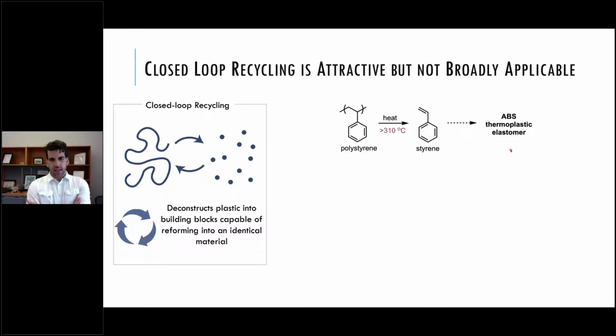A less publicized, but also I think pretty promising commercial route to do closed loop recycling is actually of polystyrene, otherwise known as styrofoam. If you heat this up above 310 degrees Celsius, sometimes you can use catalysis technology, sometimes you don't have to. This is actually above what we call the ceiling temperature of styrofoam or polystyrene, and that's when it will just depolymerize to the styrene monomer through simple thermodynamics.